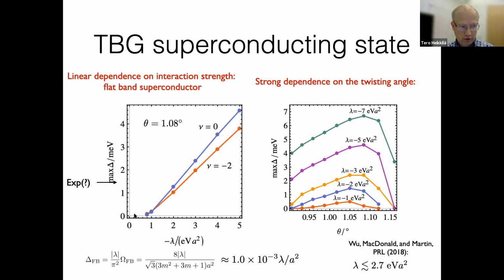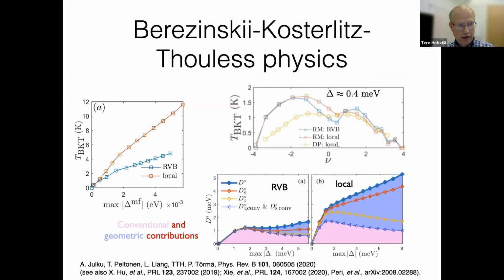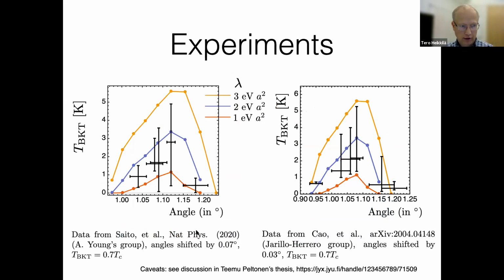There's a critical value of coupling, and then beyond this critical value, you get a linear scaling. And okay, now you can also, in this case, estimate the size of this delta versus lambda. What we also did was to do the Berezinskii-Kosterlitz-Thouless physics and study it as a function of different parameters, including the angle.